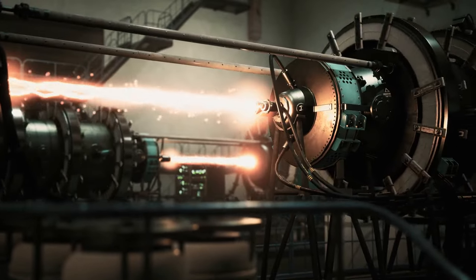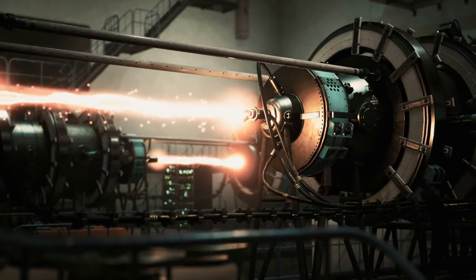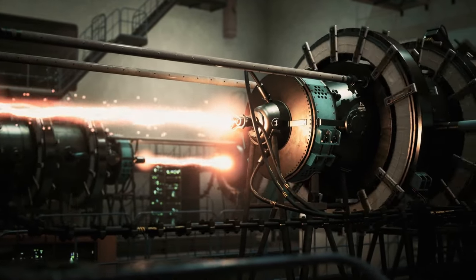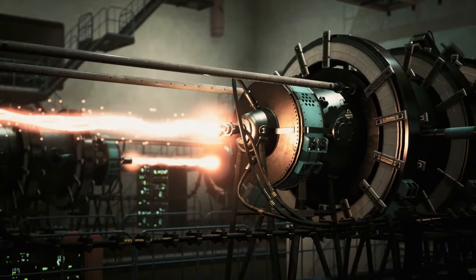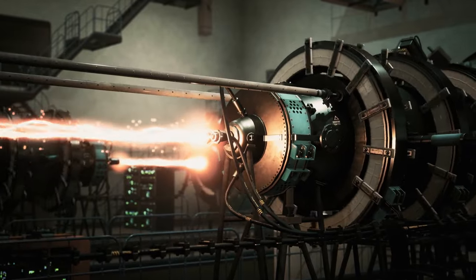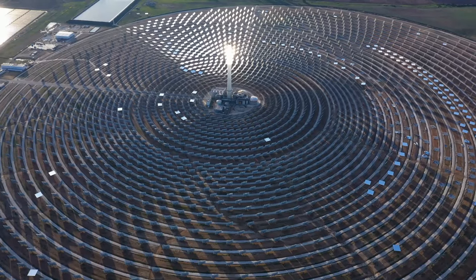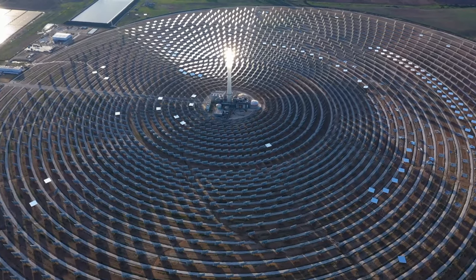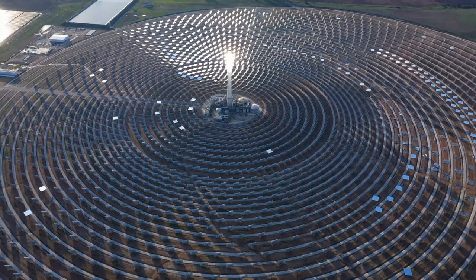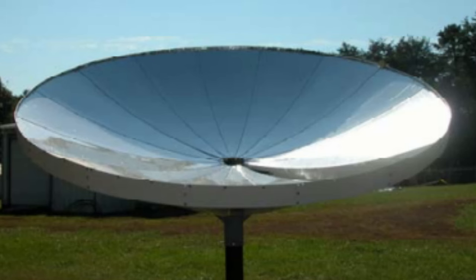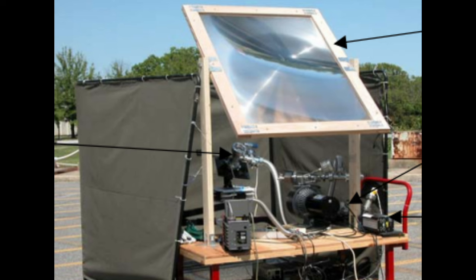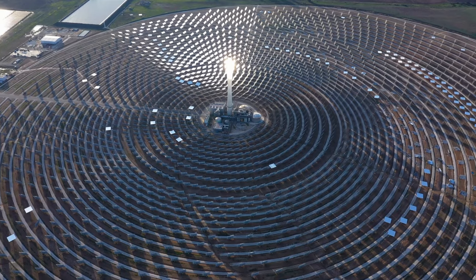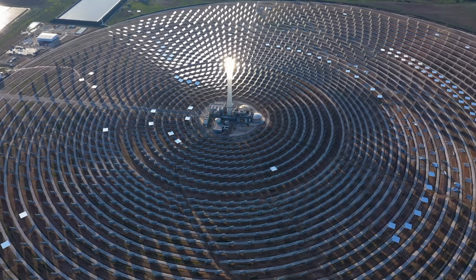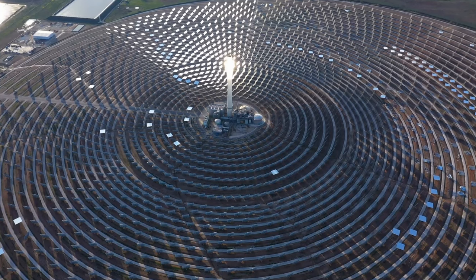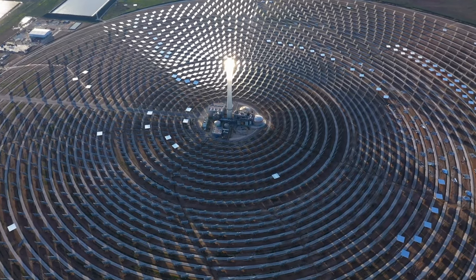One of the major problems with electrolysis is the massive amount of energy required to make it work, especially if you're using the electricity itself to heat up the regolith. But we can save about half a megawatt hour per ton by pre-melting the regolith in a solar furnace, which could simply be a mirrored dish or set of Fresnel lenses concentrating sunlight into a crucible containing regolith, heating it up before it's put into the electrolysis cell.